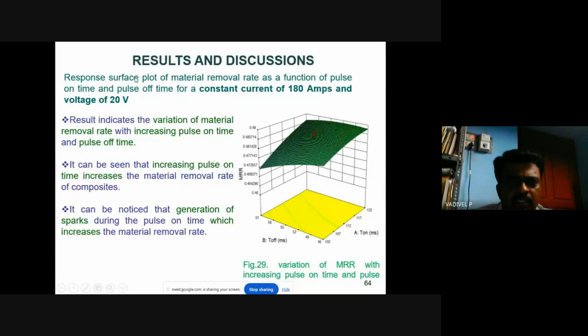This is the response surface plot for MRR as a function of pulse on time and pulse off time, for a constant current of 180 amps and voltage of 20. This graph is plotted between the metal removal rate, T on and T off. Increasing the pulse on time increases the MRR of the composite.